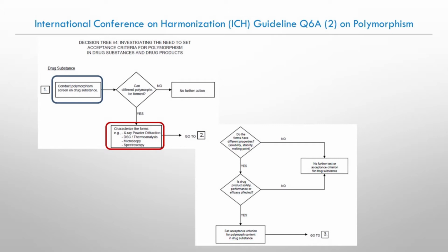If you look at the guidance, in Q6A on polymorphism, basically it's a requirement, it's an expectation that you will deliberately search for polymorphs. You need to not only monitor the batches that you produce and use throughout your development cycle, but you also need to deliberately try to vary the solvents, the compositions, the crystallization conditions in order to find as many forms of your drug as possible, and then use good science to establish which form is best for your product.